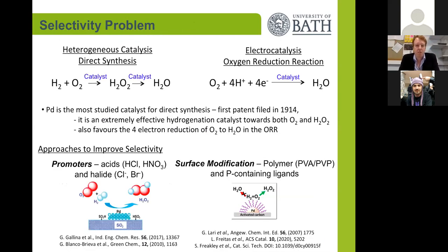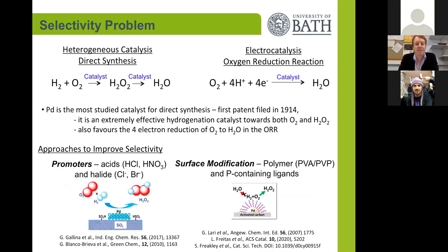Both of these processes have inherent problems and the problem mainly comes from catalyst design and selectivity. In the heterogeneous catalytic system, catalysts which are active for the combination of hydrogen and oxygen into hydrogen peroxide also tend to be active for the reaction of hydrogen peroxide with hydrogen to over-hydrogenate all the way to water.